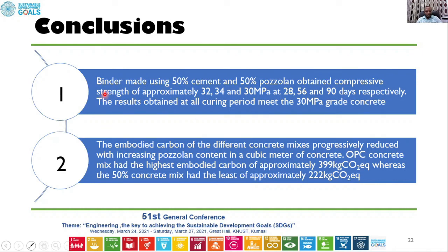Number one, the binder made using 50% cement and 50% pozzolan obtained compressive strength of approximately 32, 34, and 30 MPa at 28, 56, and 90 days of curing. So what I'm saying is that these results were higher than the characteristic strength of 30 MPa.